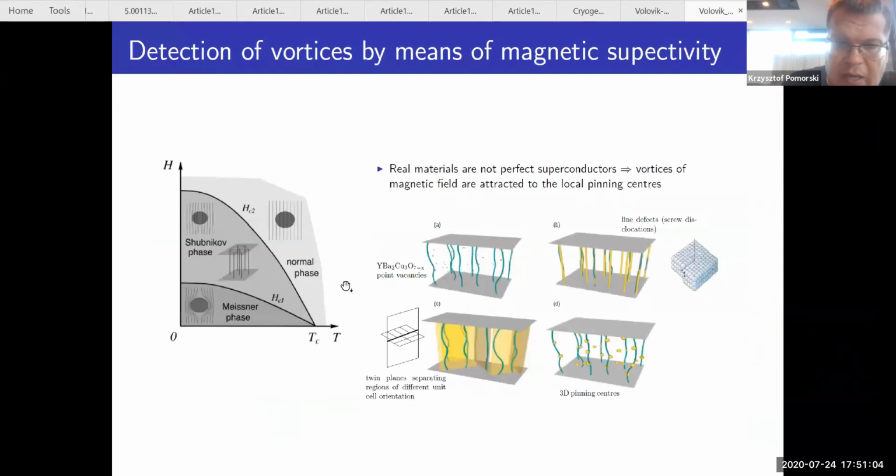And if you go further with the magnetic field, if it exceeds the so-called critical value of magnetic field, or if you start to rotate the superfluid with a velocity above the critical velocity, the system will suddenly go from the macroscopic quantum state to the normal state, where there is no order parameter due to the macroscopic quantum effect.